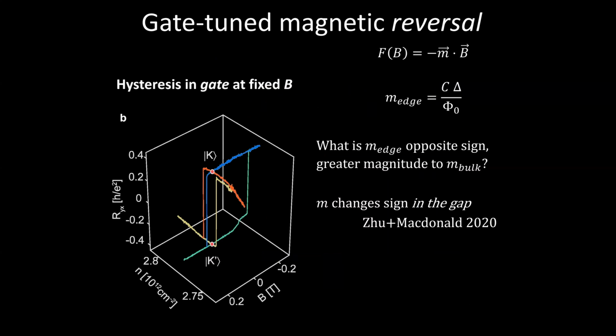But it turns out, so this is a little bit complicated to look at, but it's a 3D plot where on one axis, we're doing exactly that hysteresis loop. So in blue and green, you can see a hysteresis loop as a function of magnetic field. But you can actually achieve the exact same thing by tuning an electric field. They basically just trying to change the chemical potential in your 2D system. And you can switch back and forth between positive and negative quantized Hall conductance just as a function of an electric field. Okay, so what is going on?